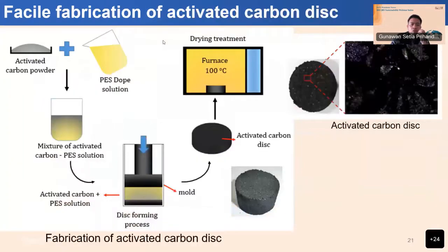So in our research, we tried to make a carbon disc using a very simple method. What we did was mix the activated carbon powder with the polyethersulfone dope solution, just like a normal membrane solution, and mix them completely. After that we used a small compaction system and pressed this mixture into a mold in the dish form.